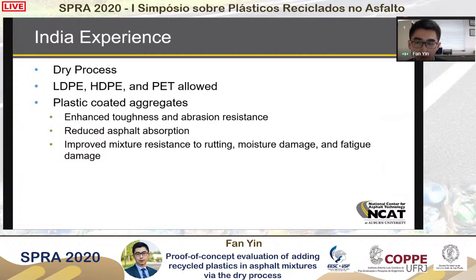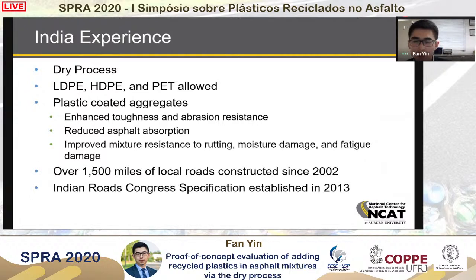And by doing that, they can improve the mechanical properties of the aggregate, including increased toughness and abrasion resistance. Also, those plastic films can reduce the water absorption and the asphalt absorption when you do the mix design. And eventually, there are some studies showing that the plastic-coated aggregate can improve mixture resistance to rutting, moisture damage, and fatigue damage. We talked with some of the contacts over there. It seems that they have constructed over 1,500 miles of local roads with this technology. But the long-term performance data of those field projects remain to be determined. And about 7-8 years ago, the agency over there, the Indian Roads Congress, established a specification that focused on the dry process of using recycled plastic in asphalt.